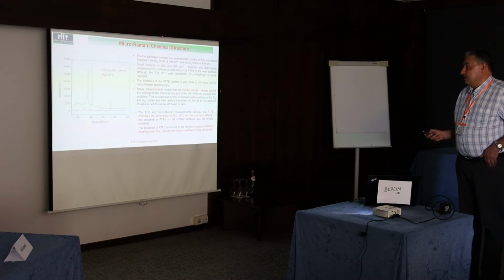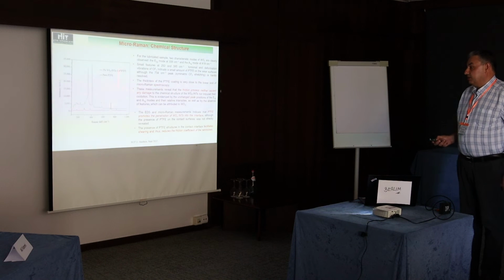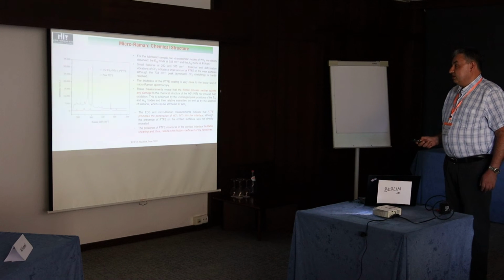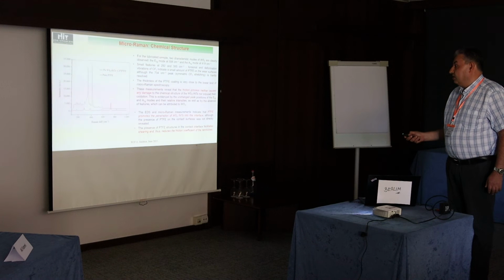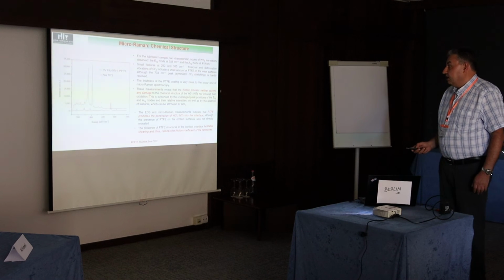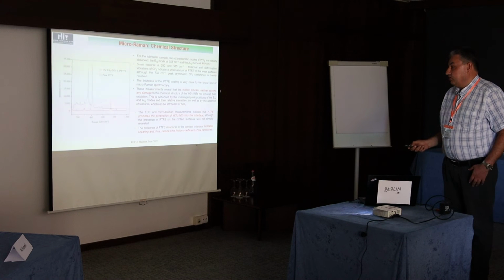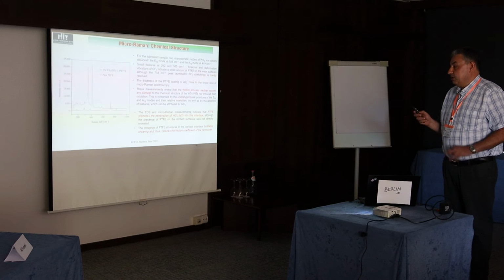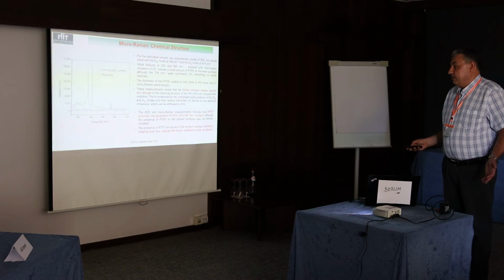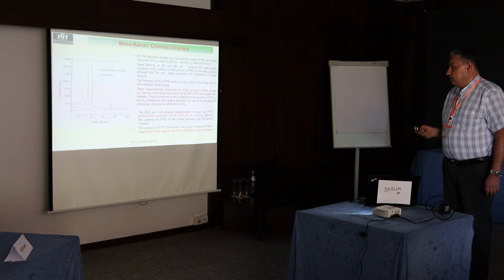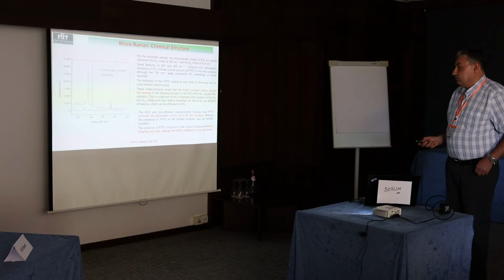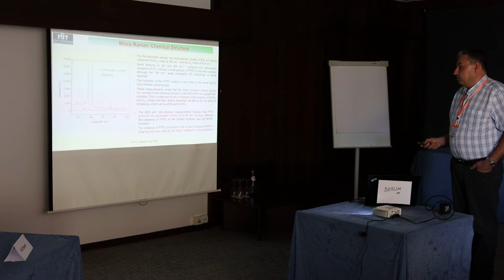This is our final analysis of micro-Raman chemical structure. So WS2 has very characteristic two peaks related to E2g and A1g, 356 and 419 inverse centimeters. This is Raman of Teflon. Here you can see these two small peaks. They are surely related to Teflon near the surface. Unfortunately, the surface sensitivity of Raman is not the best, and the thickness of the Teflon layer is on the very limit of Raman sensitivity, so probably this is why we cannot see this major peak of Teflon.